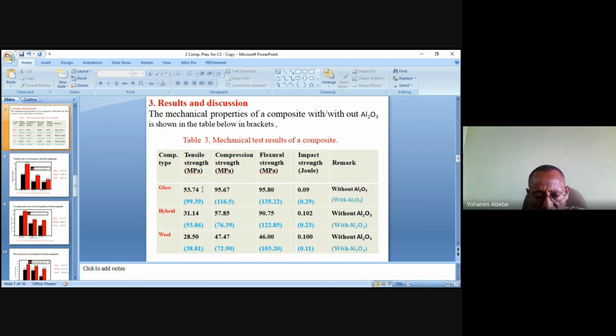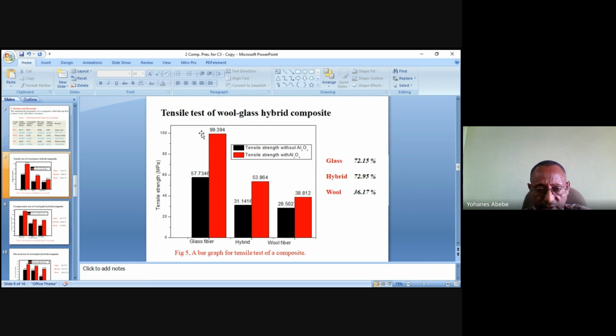So the black data is the data obtained from the mechanical test without alumina, and the red part, you can see from that, is the result obtained from the mechanical test of the composite with the addition of alumina nanoparticles. So when you see the tensile test, especially for those of the glass fiber, the hybrid, and the wool fiber, as a result of the addition, the red one is the addition of nanoparticle. The result shows that the dark part is without the addition of alumina.